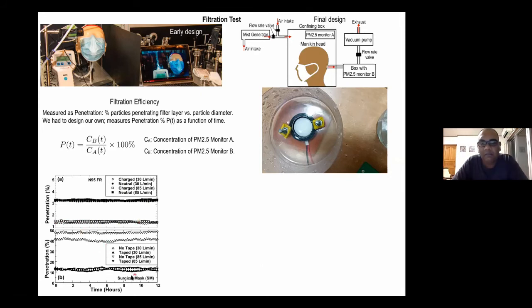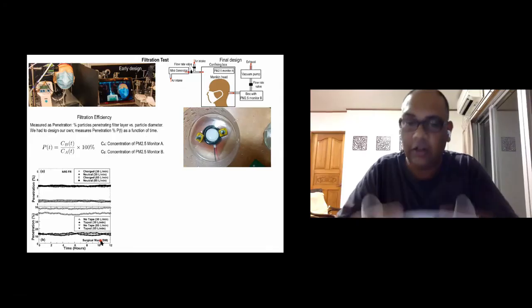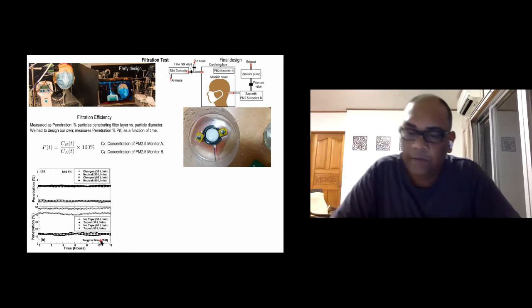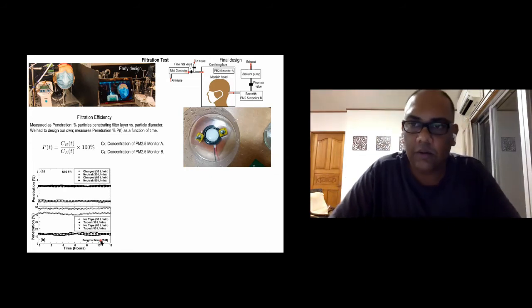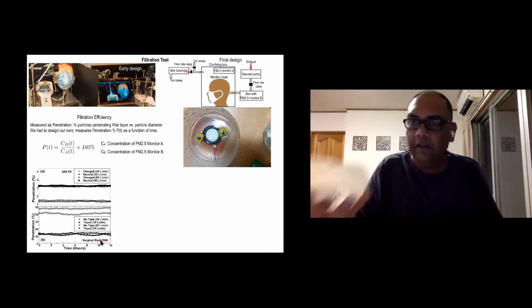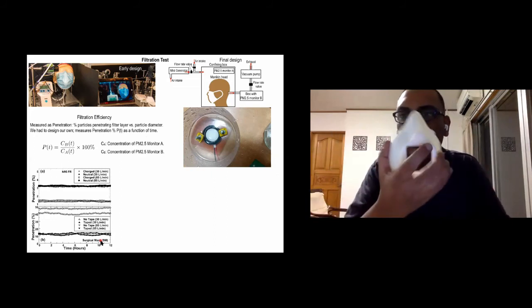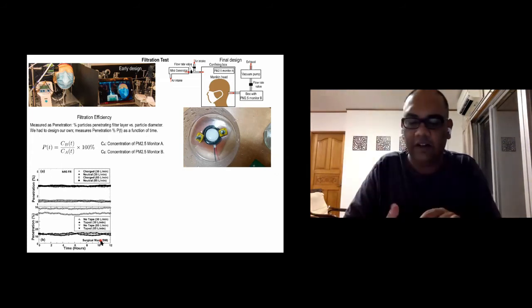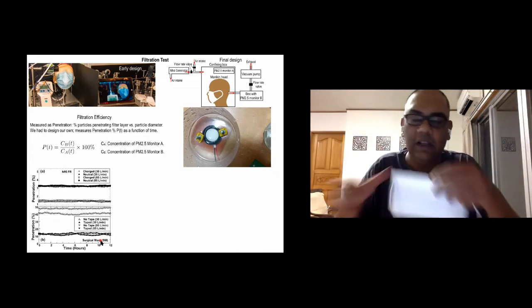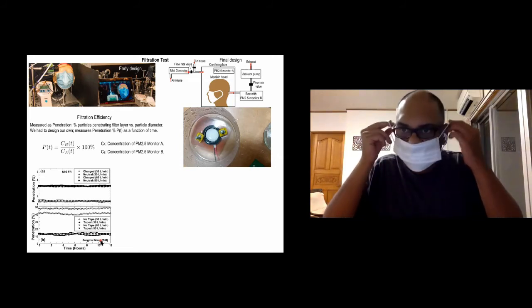Now I repeated the same measurement, not with an N95, but with a surgical mask, this type of mask. Here's the thing that is often emphasized by all health agencies, and you can find it on this N95 Decon website also, which is the tight facial fit. This 3D printed mask can give me a tight facial fit close to what the N95 achieves, but these surgical masks don't give me as tight a facial fit. There are basically these interstitial gaps through which the air can go.